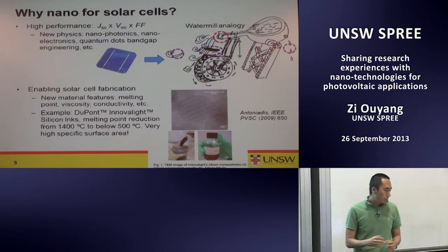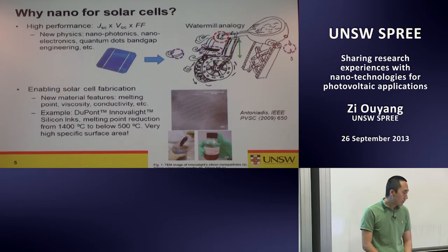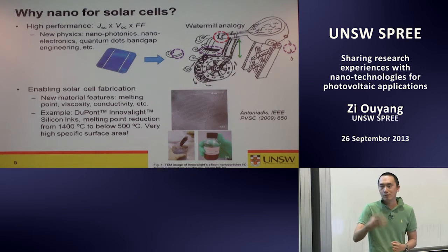But if the silicon nanoparticles are in the nanoscale, because the surface always has activation energy lower than the bulk, because it's very easy for the atoms to go out. At nanoscale, you have very high specific surface area. That means your surface area to volume is very high. So the melting point of the material actually degrades dramatically. In this case, it can be below 500 degrees, which enables a lot of solar cell processing.